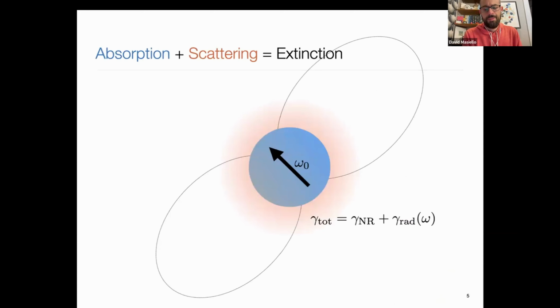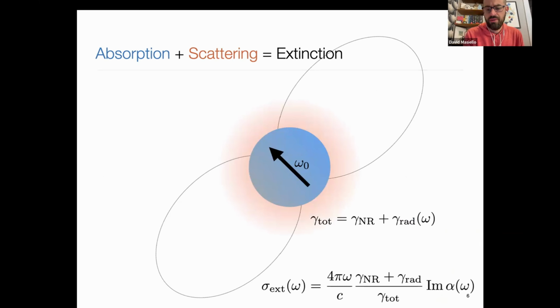Just a little bit of background here. My talk involves photothermal heating of plasmonic nanoparticles, where both absorption and scattering mechanisms are important. Particles are big enough, maybe 50, 100, 200 nanometers in size, where scattering effects actually arise and can be quite important. Of course, extinction represents the sum total of both scattering and absorption, or radiative and non-radiative processes.